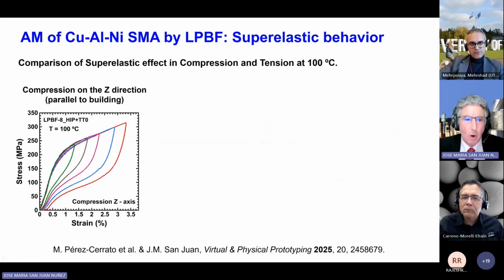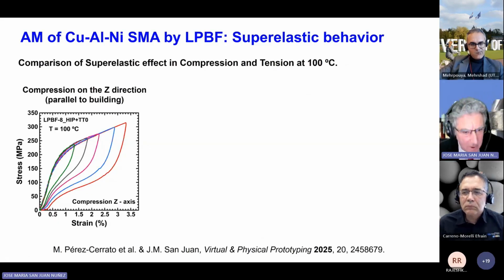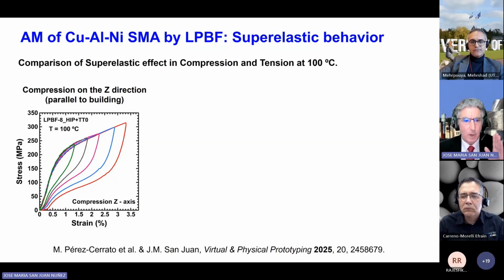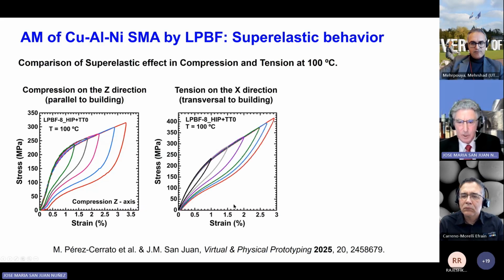But remember that we have also used the material for compression. If we do compression of the sample cut in the Z direction, we get a good superelastic behavior for lower stresses and for highest strain. When compared with the previous results in the transversal direction, we can see clearly the difference. Pay attention that the levels of the stress and the strain are not the same for the two curves.